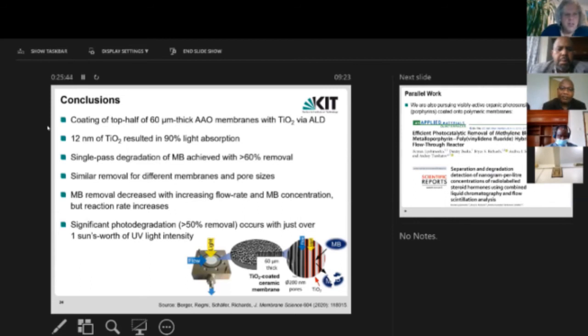Some conclusions, drawing near the end here. Atomic layer deposition was able to coat, let's say, roughly the top half of our 60 micron thick ceramic membranes with titanium dioxide. Only 12 nanometers of titanium dioxide was required to achieve 90% light absorption. And with this membrane, single pass degradation of methylene blue was achieved with typically greater than 60% removal.